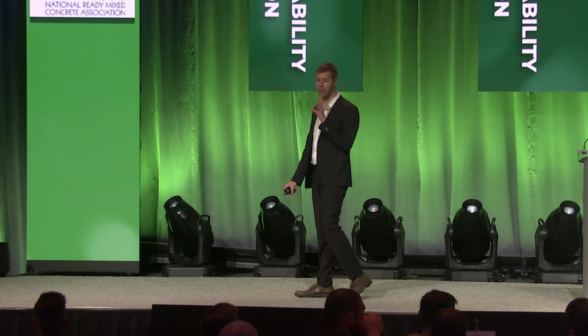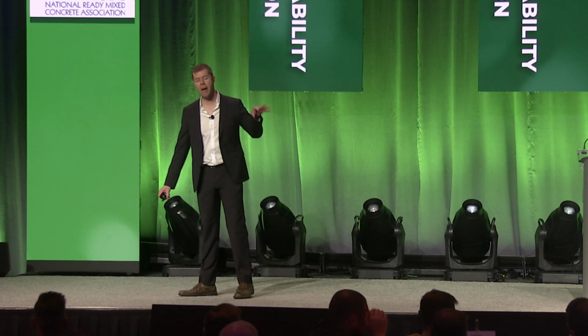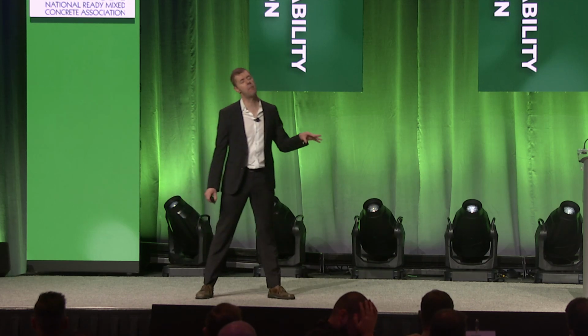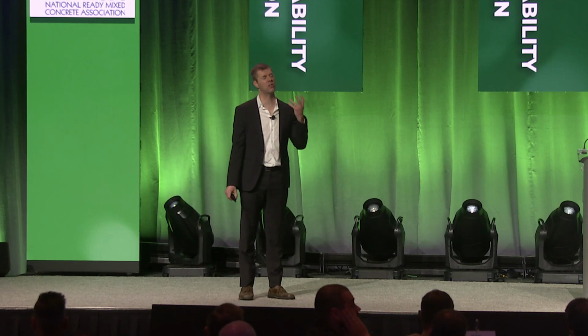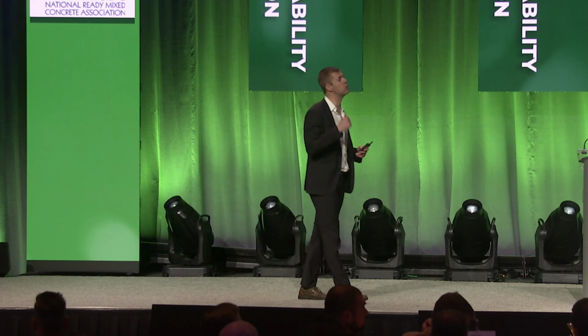What am I talking about? Water-cement ratio, it's the mass of the water divided by the mass of the total cementitious materials, the fly ash, the slag, the cement, all that stuff like that. It happens to be the most important parameter for determining the strength, the durability, and the consistency of your concrete. Extremely powerful thing here.